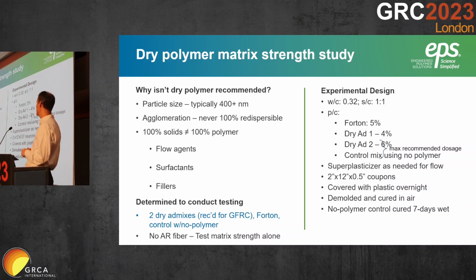of individual pieces. And then the other one is 100% solids never equals 100% polymer. In the materials that we've checked, I've seen anywhere from about 50% polymer to about 90% polymer. And the remainder of that is either flow agents and surfactants, which you need to make sure that they can redisperse, and then there's fillers that are added in there to help with the flowing and whatnot in the system. So know what you're getting.